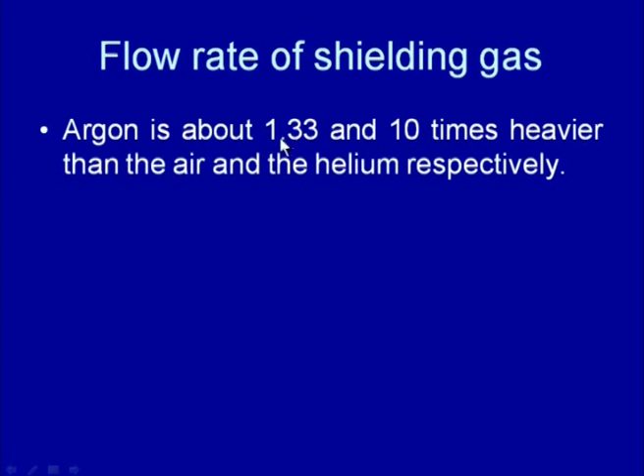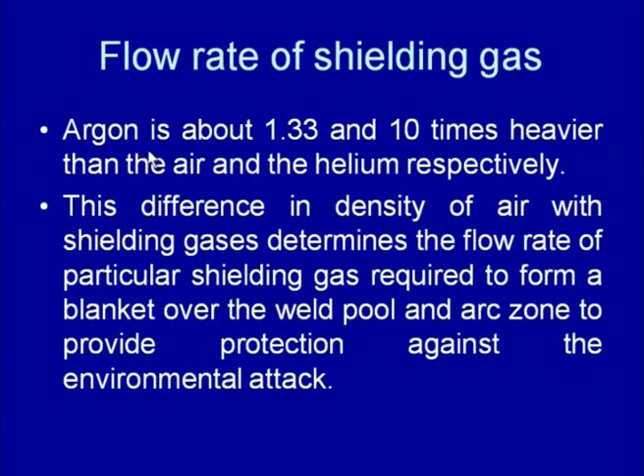The argon is about 1.3 times heavier than the air and about 10 times heavier than the helium. If we see the density of argon, it is found to be 1.3 times that of air and about 10 times heavier than helium. And because of this difference in the characteristics of argon as compared to air and helium, we find a lot of difference in the flow rate which is required.